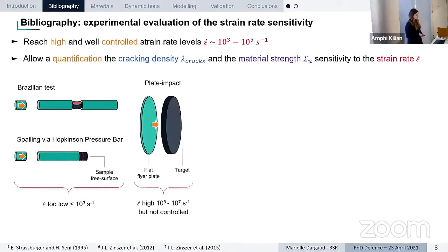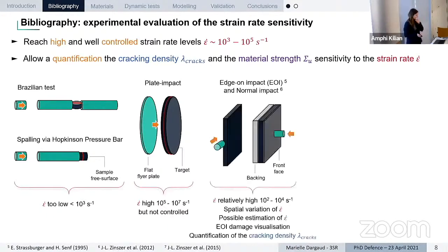To reach higher level of strain rate, we can use the plate impact configuration, which allows to reach very high strain rates. And with a spalling configuration, we can generate a tensile loading. However, in this configuration, we don't manage to reach a controlled strain rate in the material in the failure area. The next type of tests are fragmentation tests, which can be edge-on impact tests and the normal impact test. So these are two configurations that exist in the literature and provide a relatively high strain rate, which can be estimated.